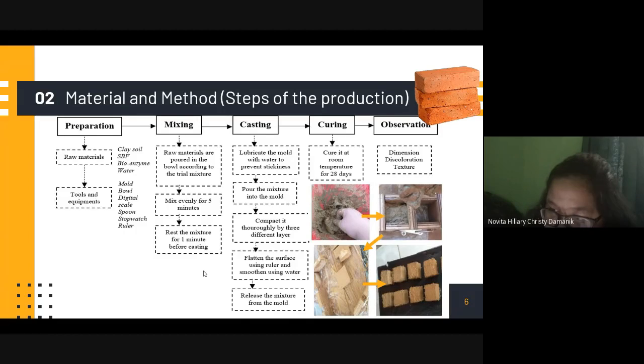In the casting part, first lubricate the mold with water to prevent stickiness, and then pour the mixture into the mold and compact it thoroughly in 3 different layers. And then flatten the surface using a ruler and smoothen using water. After that, we release the mixture from the mold. After releasing it, cure it at room temperature for 28 days. And after 28 days, we will see the dimension, the discoloration, and the texture.